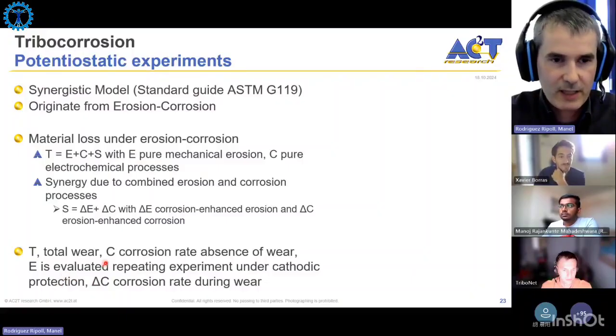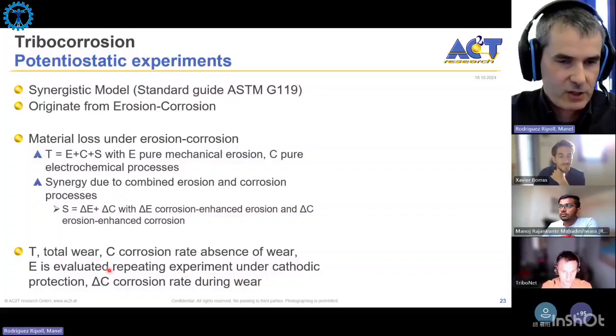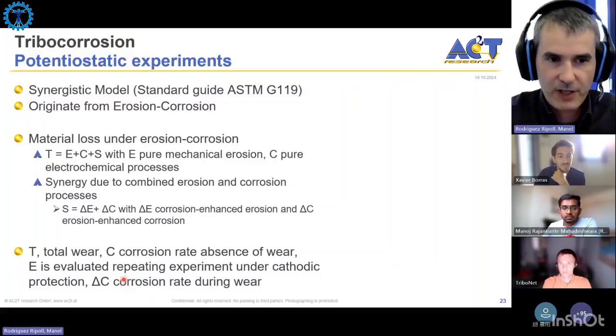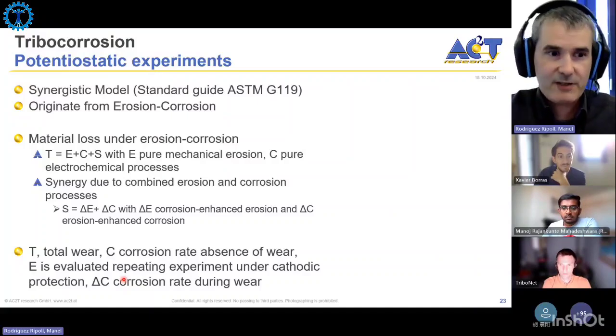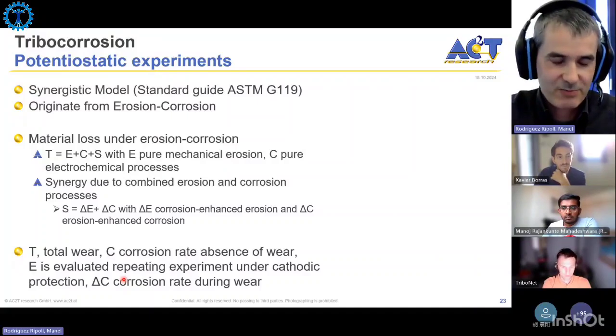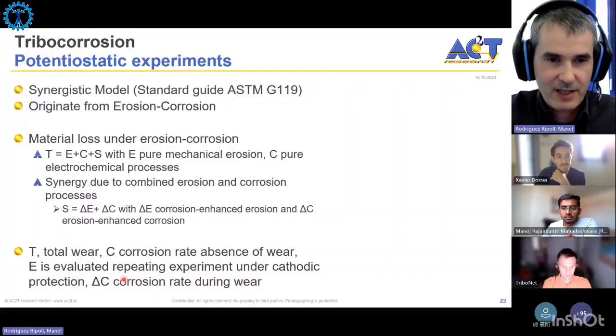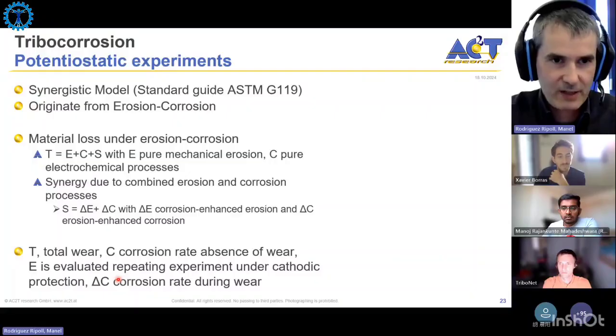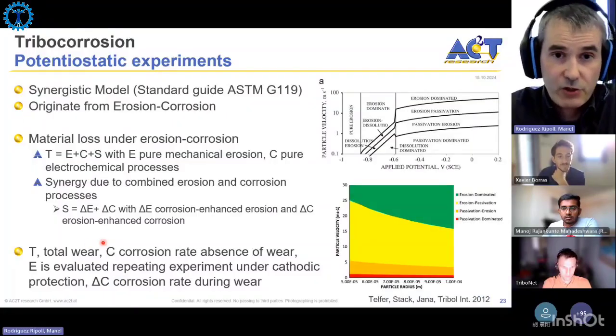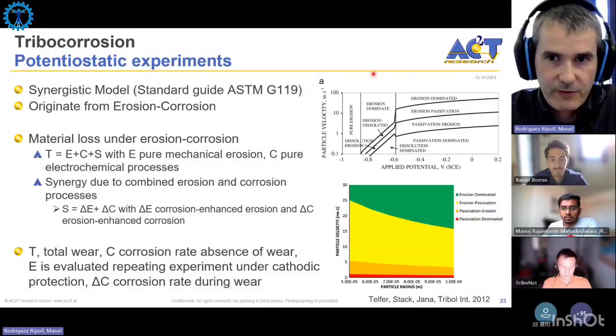And also, to get the polarization curve during the wear experiment, you have the problem that the polarization curve takes some time to be measured. So normally the scan rate is small. And during this time, you can trigger the formation of wear debris, you form third bodies, you change your microstructure. So maybe at the end of your polarization curve, your metal is different than it used to be at the beginning. So these are probably the main critics of this model: the difficulty to get these terms independent from each other and their accurate physical meaning. But it's still widely used in literature, and then you can make, for example, this kind of maps as well.